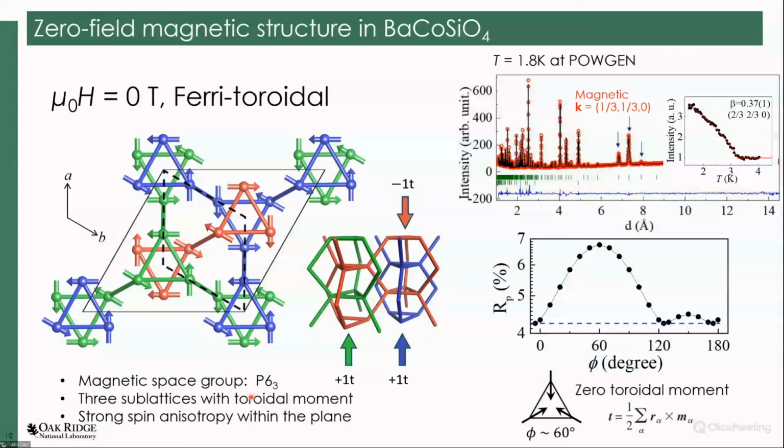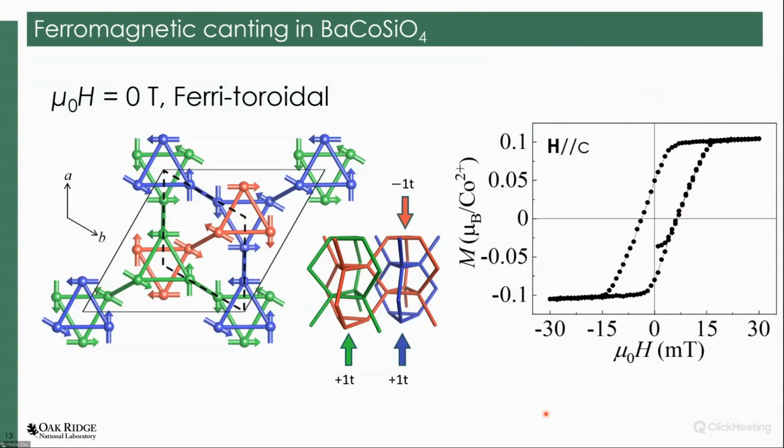Those are certain positions. At 60 degrees, the worst refinement quality gives a spin all in or all out. That's the typical Heisenberg interaction we expect. This kind of magnetic order wouldn't give any toroidal moment, so they cancel. And that's what we got from a powder sample.